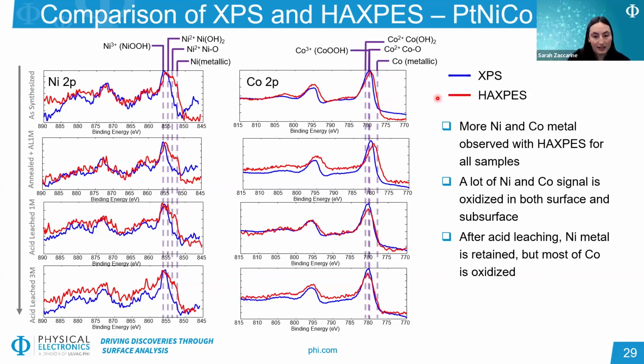We can again look deeper into the sample with the HAXPES source, which is the red spectra, and here we are starting to see more nickel metal in the subsurface with all of these different post-processing steps. We do still see a bit of a change in the shape with processing, and generally we still see some nickel oxides present in all cases. With the cobalt data, with the HAXPES source, we do start to see some cobalt metal with the as-synthesized sample and the one that was annealed. But after acid leaching, the XPS and HAXPES data look quite similar, and we're really just seeing predominantly oxidized cobalt.